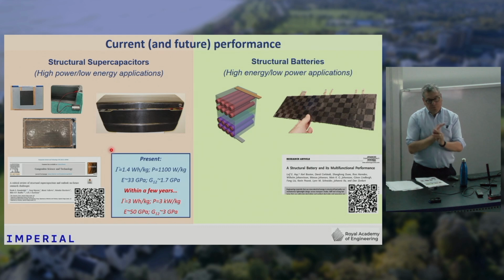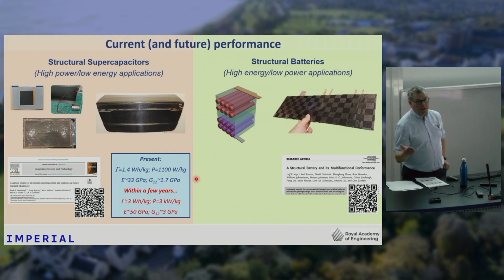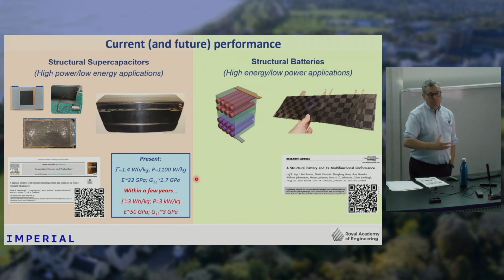So just to give you an idea of where we are, a conventional supercapacitor will store about 5 watt-hours per kilogram and has a power density of about 5 to 10 kilowatts per kilogram. We're sitting at about 1.4 watt-hours per kilogram and 1.1 kilowatts per kilogram. So we're not as good as a conventional supercapacitor, but then we have a material that you can build a table out of, for instance, which you can't do with conventional batteries or supercapacitors.